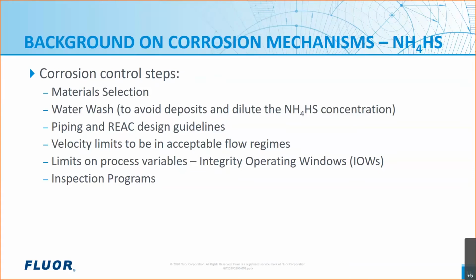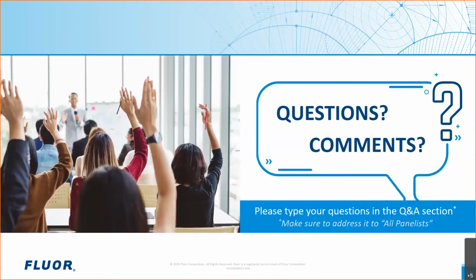In any systems that have carbon steel in the area of the REACs, just about everyone has way more inspection thickness monitoring locations and does the inspections much more frequently than other systems, just since there is a risk of corrosion and you want to even try to detect any onset of corrosion before it gets significant. So you can see that this is a very important mechanism for the industry, and that's why there's some very good industry standards on it. So this is a good break point.